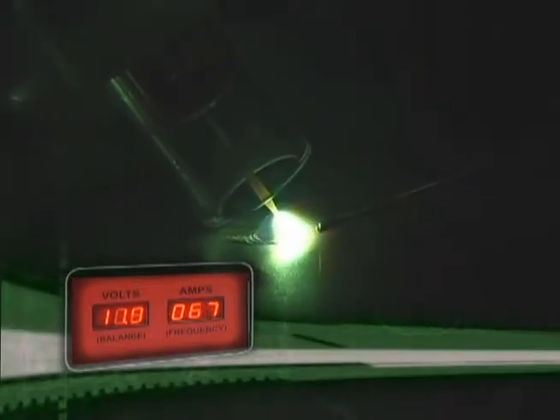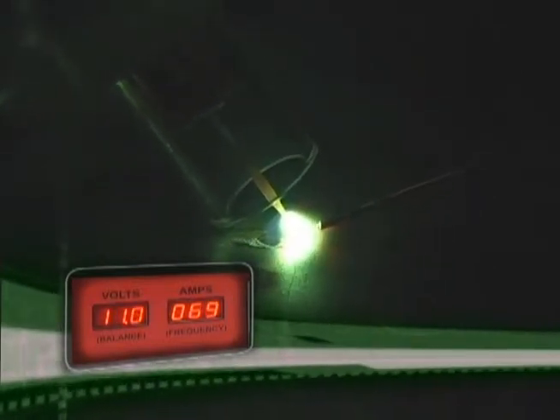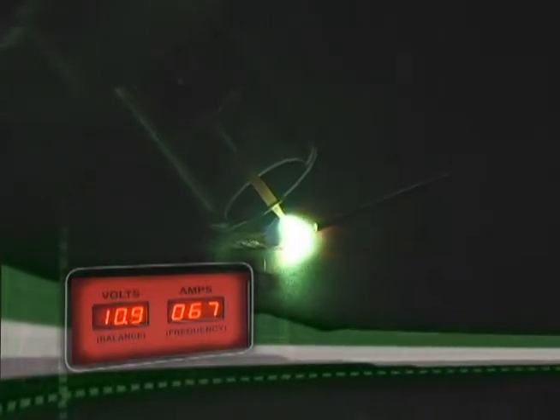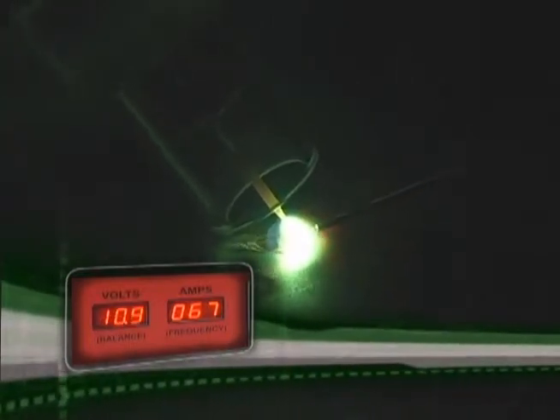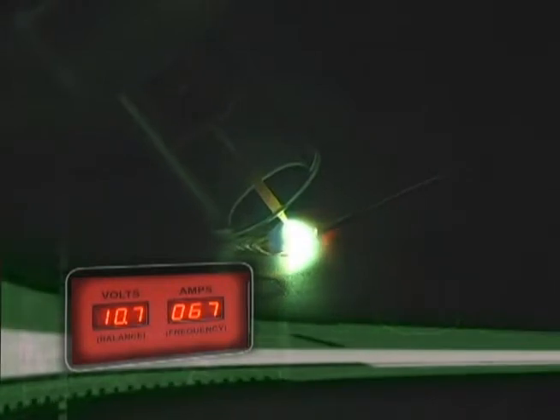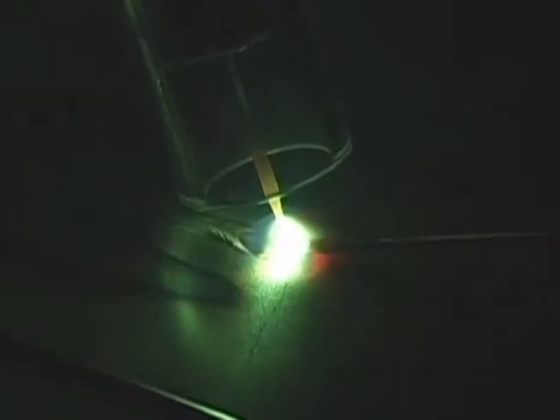Continue to dab the filler metal into the leading edge of the puddle. If you can dab the filler metal, say every 1/2 a second, just like a robot, at a constant rate, it will give you that nice row of dimes look. While you are dabbing the filler, remember to move the torch at a constant speed and height, and adjust the foot pedal to control the puddle and maintain a constant bead width. You dab the filler into the leading edge of the puddle.